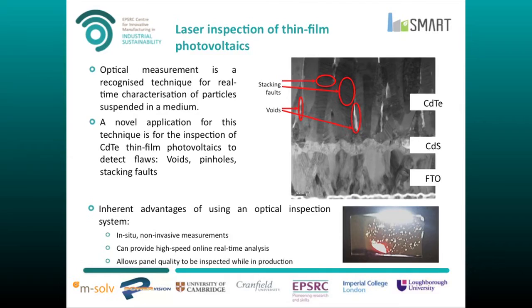So voids, on an SEM image of the layer, here's some voids, stacking faults. Shine a light through it, you can see pinholes. These are all flaws that appear during the manufacturing process and can cause degradations in the performance of the cell. So we have certain advantages to using an optical inspection system versus using an SEM or an electron microscope system. First one being that we can do it without moving the sample. So in situ, in a production process, we can shine a laser at it and we can measure the production flaws in progress. It can be done at high speed and in real time.